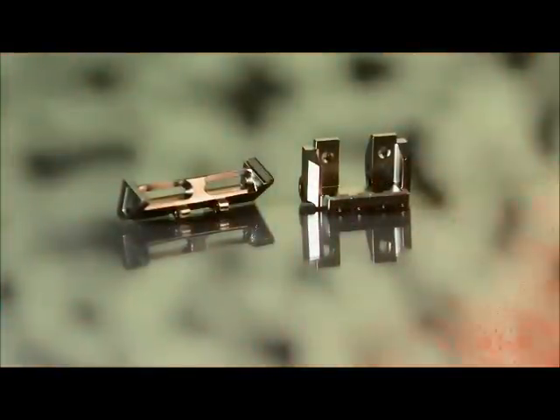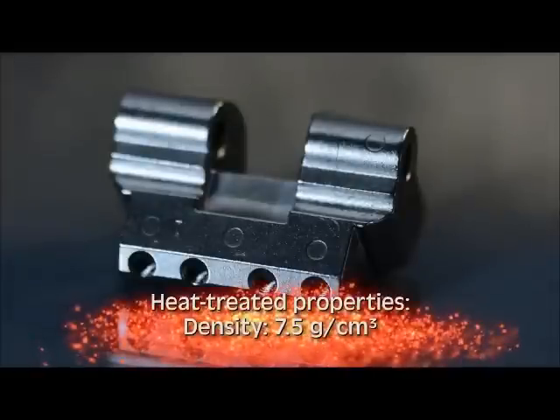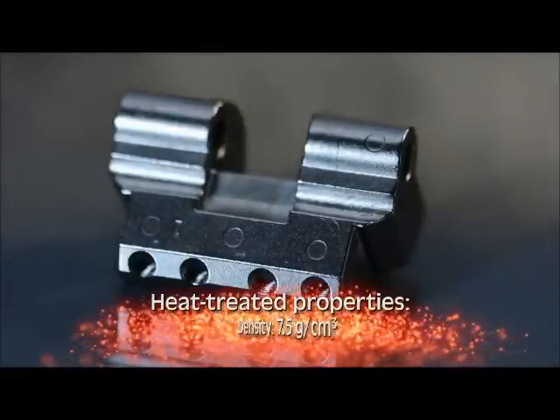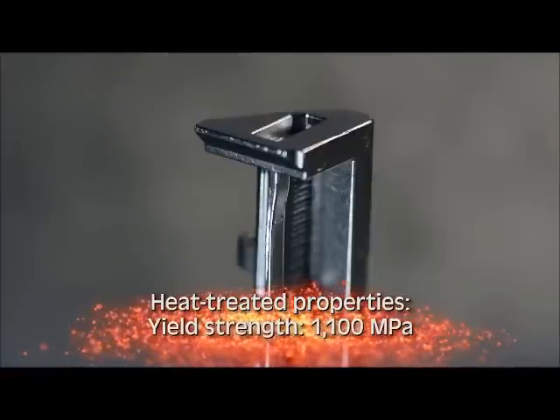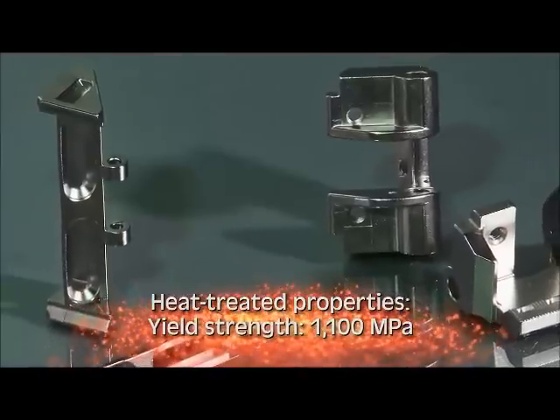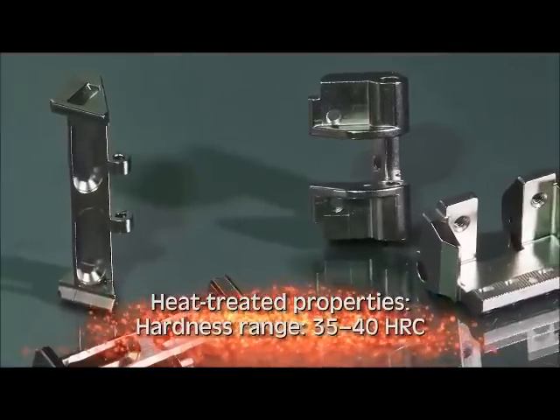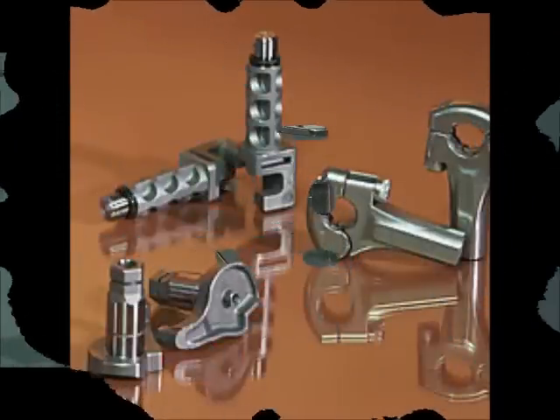The part's complexity, with many crossholes and sharp knurl features, required the use of multiple slides, some moving at different angles. The parts are made close to net shape, requiring only a final coining to adjust a small distortion and a tapping operation on the front keeper. Annual quantities are 20,000 per part.